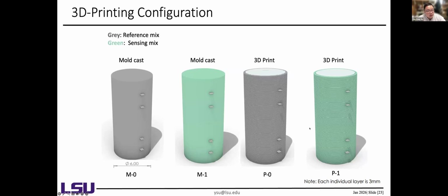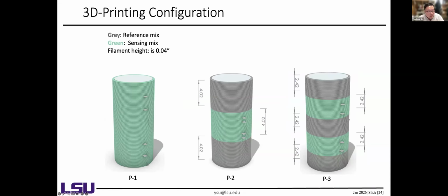And in terms of the 3D printing, we firstly try some small sample, try to figure out if that work, and with different printing configuration. As you can see, we have the molds. We compare the molds with all reference mix, which in terms of the gray, and the green refers to the sensing mix. And we also print the shell and grout with the concrete inside, and try to understand if we can see the good signal to compare that.